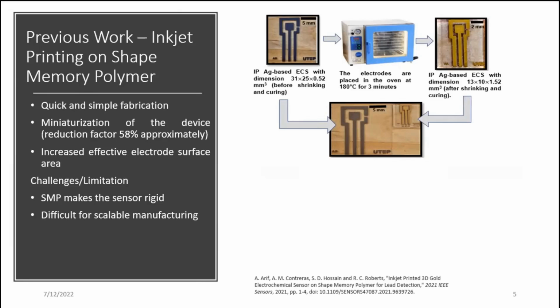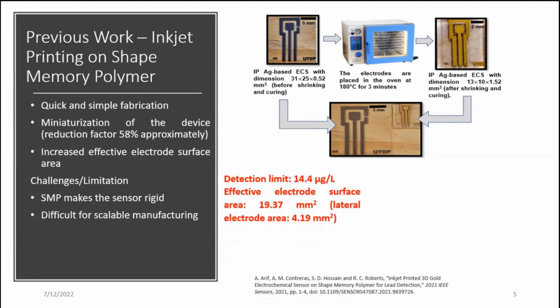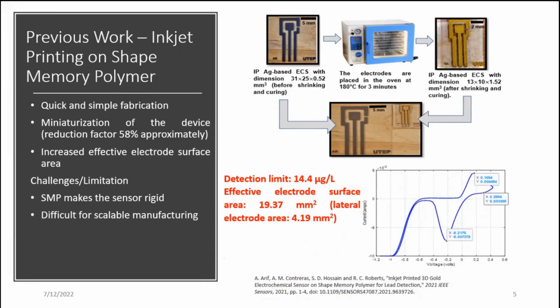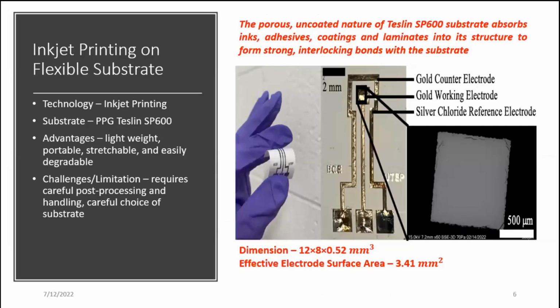We offer this combination because of simple and quick fabrication as well as miniaturization of the device, because we got like 58% reduction in terms of dimension for our electrochemical sensor. And also we were able to see increased effective electrode surface area compared to lateral surface area because of that crunching and twisting mechanism of shape memory polymer. And we were able to see a very good performance for our fabricated electrochemical sensor in case of 14.4 microgram per liter lead. We have chosen this concentration because in the United States, according to US Environmental Protection Agency, the maximum allowable lead level is 15 microgram per liter, but we are currently working to push this concentration as low as possible. So here we are for our inkjet printed electrochemical sensor on shape memory polymer.